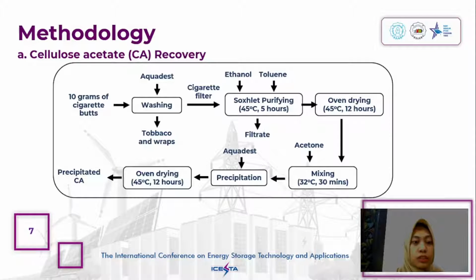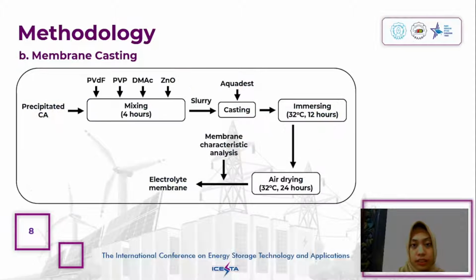The first methodology is to recover the cellulose acetate from cigarette butts. We wash the cigarette butts to separate the tobacco and the wraps from the cigarette filter by adding aquades, and we will purify them by adding ethanol and toluene. We will get the residue, dry it in an oven for 12 hours, and mix it in acetone and precipitate it into aquades, and we will dry it in the oven, and we will get the precipitated cellulose acetate.